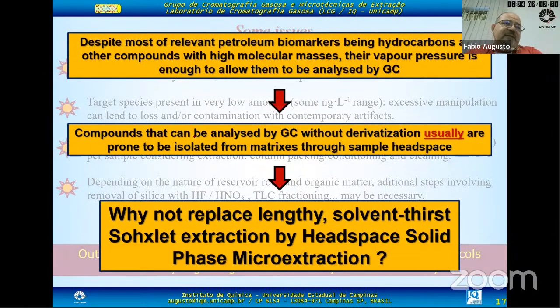But why not simplify that using solid phase microextraction? Most of the relevant petroleum biomarkers are compounds with high molecular masses, with very, very low volatilities, but they have a vapor pressure high enough to analyze them by GC. So if you can analyze a compound by GC, the general rule is you can extract it by some headspace technique, although for those compounds this is not usual. Most people would not see those compounds, gammacerane, etc., as compounds you analyze with any headspace technique, especially headspace solid phase microextraction.